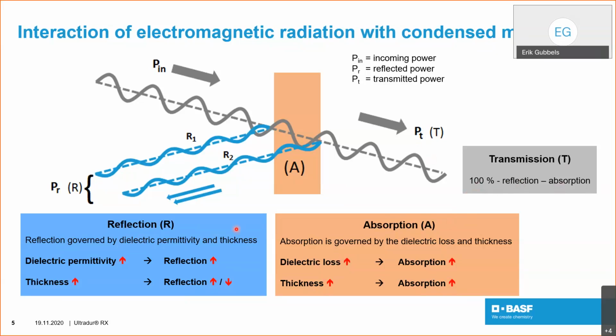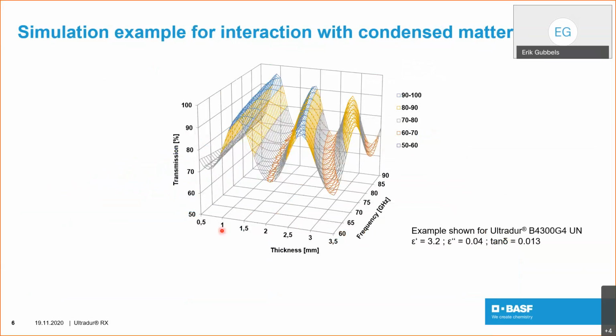We briefly mentioned the thickness dependence of absorption and this interference pattern, which can be obtained depending on the thickness. And this we want to elaborate a bit further for you. Here you see a simulation of a material. It is an Ultradur B4300G4 uncolored, which is not an absorbent material, but more suitable, for example, for a transmittant material, which has a dielectric permittivity of 3.2 and a dielectric loss of 0.04, which is very, very low. And as we'll show later, this is not an efficient absorber, therefore. One can immediately see a very dependent behavior based on the frequency and the thickness of the material. And this is this constructive or destructive interference pattern I spoke of on the last slide.